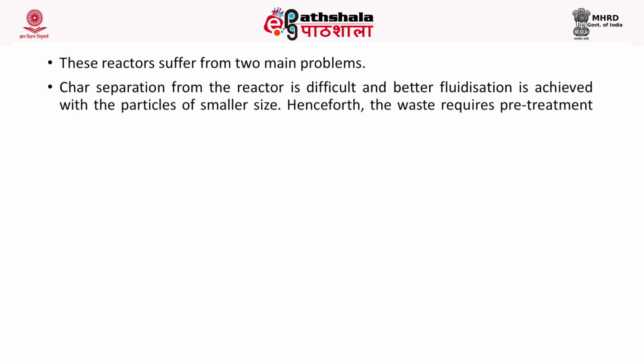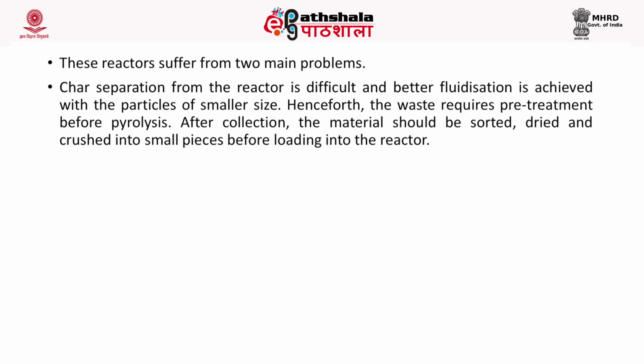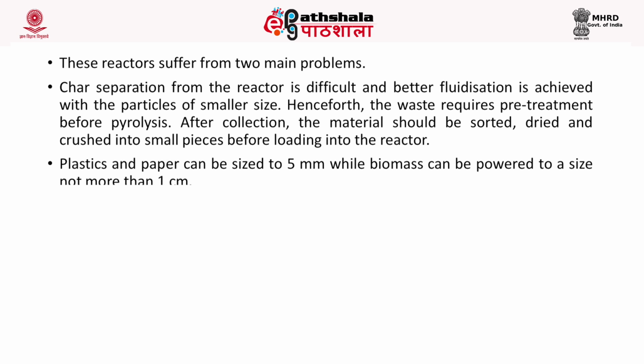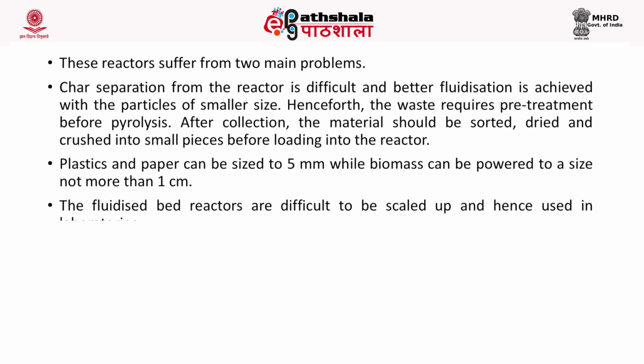However, these reactors suffer from two main problems. One, the char separation from the reactor is very difficult and better fluidization is achieved with the particles of smaller size. The waste requires pre-treatment before pyrolysis, and after collection the material has to be sorted, dried and crushed into small pieces before loading into the reactor. Now, plastics and paper can be sized up to 5 mm, while the biomass should not be more than 1 centimeter before adding into the pyrolysis unit. The fluidized bed reactors are very difficult to be scaled up and hence normally used in laboratories.